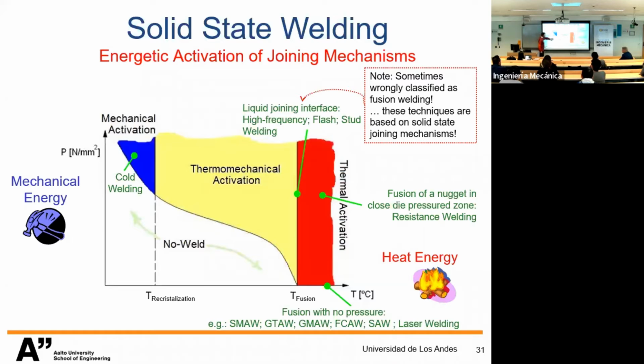key knowledge for innovation. When the materials are very ductile, mostly face centered cubic structures, we can have processing in cold, low temperature without recrystallization, because these dislocations require very low level of energy dissipation, and we have the cold welding concept. And examples of this, we will see that the long kilometers of wires in bobbins and so on, they are extruded in copper, aluminium, even steel, but they don't come with kilometers. So the wire systems have to be welded together. So cold welding is quite applied in that field.